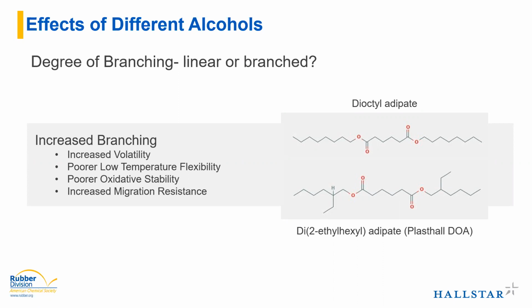The reason behind this is if you think of your polymer matrix as an entanglement of long chains, the more branches you have on your plasticizer, the less freely that plasticizer will be able to move between the chains because those branches get more entangled. That allows for less overall mobility, giving you worse low temperature flexibility than with a simple straight chain. You'll also see poorer oxidative stability. There's more sites in the molecule that are ready to be oxidized. So you'll see worse stability in that area.